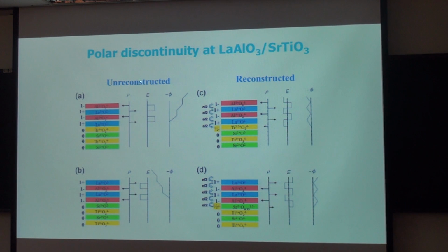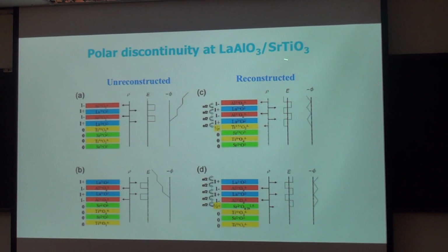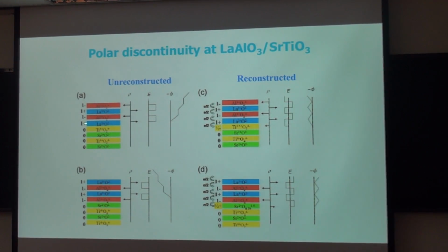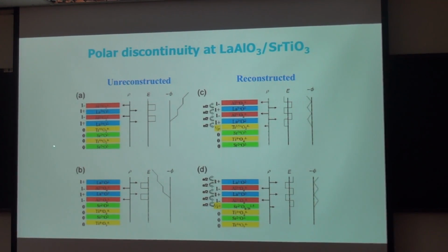In fact, this is a picture of polar catastrophe, which describes the polar discontinuity at the interface of two insulators. When we deposit this polar material on a non-polar material, we can find that there is a polar discontinuity developing along the perpendicular direction of this film.